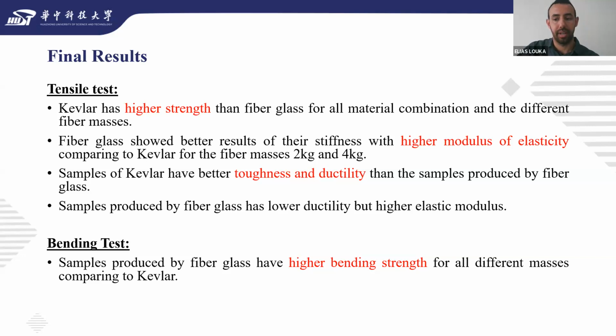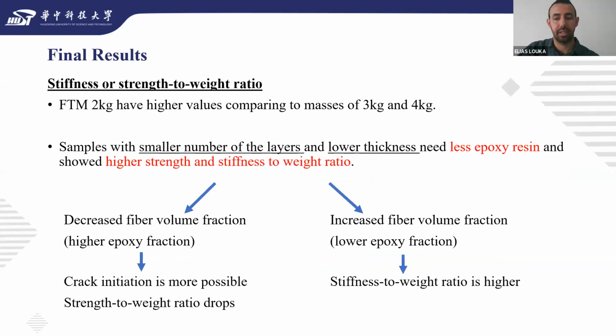Samples with a smaller number of layers and lower thickness need less epoxy resin and show a higher strength or stiffness to weight ratio. This leads to the conclusion that with decreased fiber volume fraction, which means higher epoxy fraction, crack initiation is more possible. This is why the strength to weight ratio drops. Additionally, with increased fiber volume fraction, which means lower epoxy fraction, the stiffness to weight ratio proves to be higher, as expected.